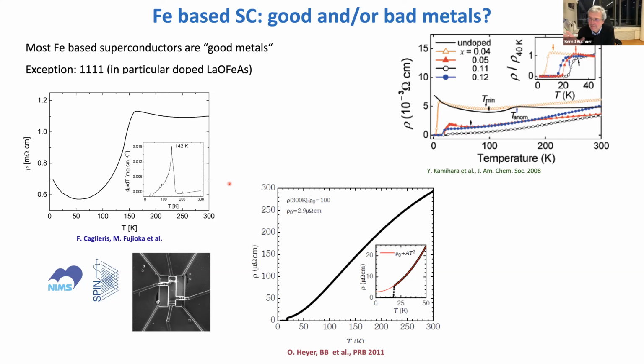So let me first, maybe, make a short remark on the similarities and differences between 122 and 1111. What remains is this remarkable difference in the normal state: we really have a system which is close to an insulating state. If you look at the resistivity, it's really different. So the coupling is much stronger here. I don't think that this is really understood. What is definitely the case is that we have a more two-dimensional system, not this intermetallic behavior, not a 3D system. We have this oxygen in there. Maybe the lattice coupling is stronger. I don't know, but this remains.